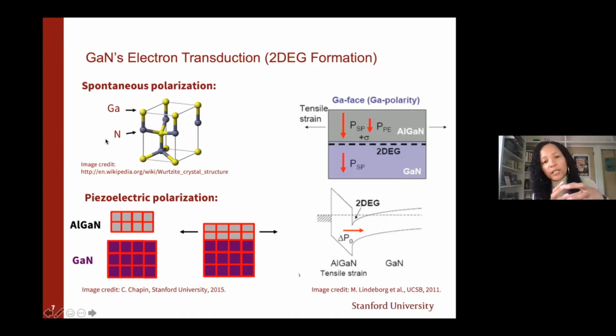So if I look at a unit cell of gallium nitride, it has asymmetry. And so there's a dipole that's present in a unit cell crystal. And then also there's piezoelectric polarization. So if I grow a slightly doped variant of gallium nitride, let's say AlGaN, aluminum gallium nitride, on top of a gallium nitride lattice, due to the lattice mismatch, this AlGaN layer is in tension. And the combination of these two effects actually leads to the formation of the two-dimensional electron gas,